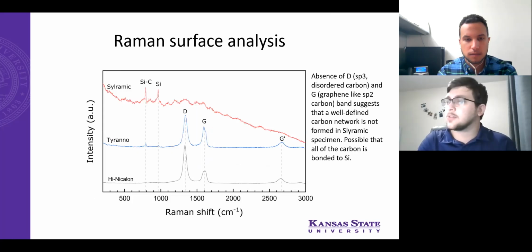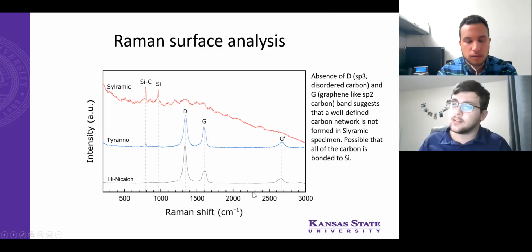Then there was Raman surface analysis done, showing some excess silicon on the surface, as well as excess carbon in the Tyranno and Hi-Nicalon samples. The absence of D and G bands suggests that a well-defined carbon network is not formed in the Sylramic specimen, and it's possible that all the carbon is bonded to the silicon. So, excess carbon atoms in the Tyranno and Hi-Nicalon versus excess silicon in the ceramic.